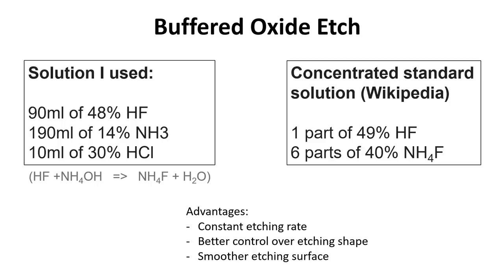Before I started working with it, I made so-called buffered oxide etch. Basically this is HF diluted with an ammonium fluoride solution. I actually made a less concentrated solution than the standard. The way I made it was by slowly adding a surplus of concentrated HF to a concentrated ammonia solution. And in addition, I added a small amount of hydrochloric acid, since this is known to give smoother etching results by dissolving reaction products.